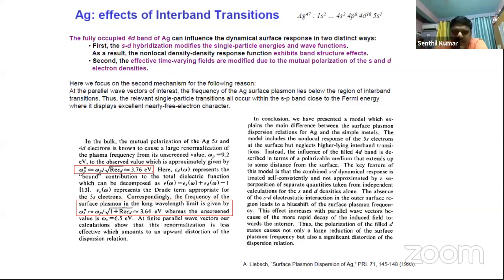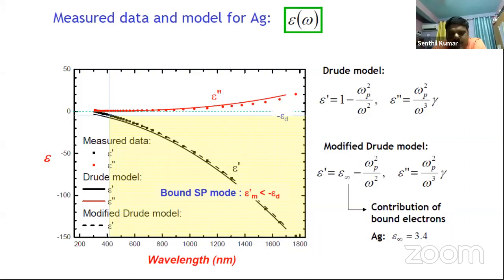As you can see here, after incorporating the interband or bound electron contribution to the silver data, it matches. The dots or arrows are the experimental data, and the line is the theoretical data, and it matches. That is the effectiveness of the Drude model. That's why it's called the modified Drude model once you incorporate this epsilon interband transitions. For Ag, the epsilon infinity or epsilon interband transition is around 3.4. Experimentally they found this out, and the experimental data is satisfied.